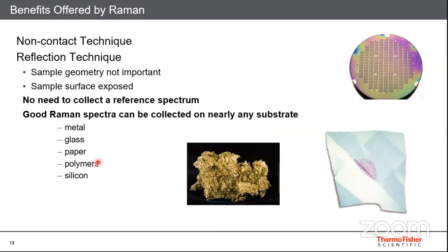Another important thing offered by the Raman is that it's a non-contact technique, it's a reflection technique, and therefore the sample geometry does not matter much. So even if it is an uneven surface, you can use Raman spectroscopy. It gives you very good spectra nearly on any substrate, whether it's metal, glass, paper, polymer, silicon. Well, it gives you very good spectra.